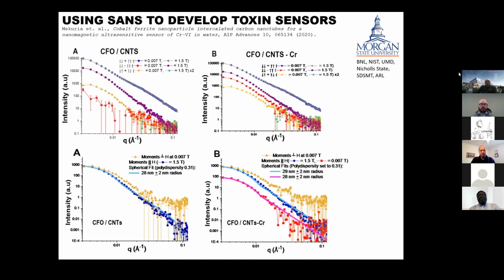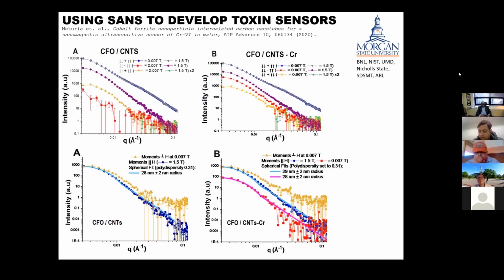The other thing it shows is that whenever you apply a magnetic field and then take it away and look at the remnants, there's no hysteresis in just the nanocomposites. But if they were infiltrated with the chromium, there is hysteresis, meaning that there's a remaining magnetic field. Now, this is really cool because I don't know if the researchers knew this going into it, but they were able to uncover two different routes that you could conceive of to use this system to detect the hexavalent chromium. One is looking at the enhanced magnetization, which seems to be a fairly straightforward effect and borne out by the data. But also the fact that there's a remnant effect. There's a remaining magnetic field after it's been infiltrated with the chromium, and then you apply a field. So I like that because that's a really nice example of a potentially quite practical application of neutron scattering in functional materials.